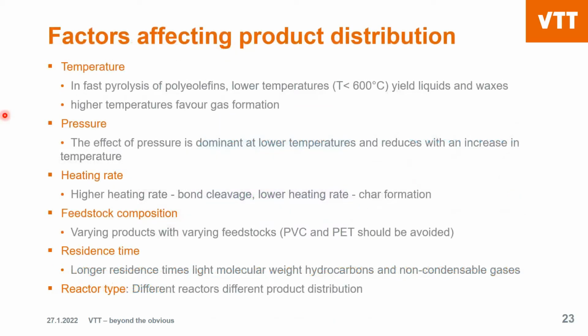What are the factors that affect the product distribution? So what are the factors that basically define what your product would look like from the pyrolysis? Temperature, pressure, heating rate, feed composition, residence time, and the reactor type are all factors that influence your product in the end. In fast pyrolysis of polyolefins at lower temperatures, you get liquids and waxes at less than 600 Celsius. If you go to higher temperatures, you favor gas formation. Pressure has not so much effect. The effect of pressure is dominant only at lower temperatures, but at high temperatures it is not relevant. Heating rate is very relevant.